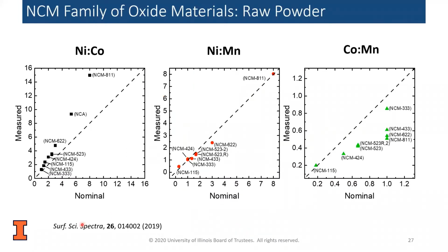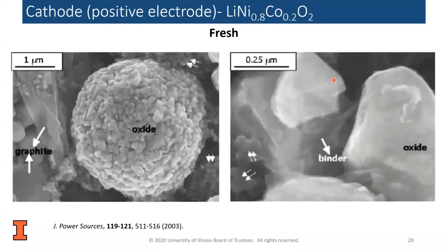If you look at the compositions as they vary with the family of the NCM, the high nickel containing oxides tend to reside more at the surface than the lower ones. The manganese seems to occur much as we expect the composition to be. And then it appears that cobalt resides below the surface. So it looks like the nickel is on the top and the cobalt is down below. This will be important because this possibly indicates the mechanism of rapid decomposition by having excess nickel at the surface.